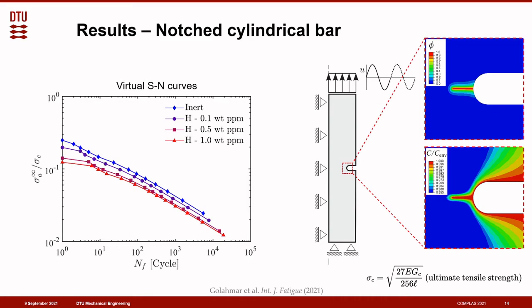And on the right side, I'm showing two contour plots. The one at the top is the evolution of the phase field parameter. The blue color corresponds to undamaged material points, while the red color corresponds to a crack. So basically, you can see how the model captures fatigue crack nucleation and propagation from a notch and in the absence of a stress singularity. And the other contour plot at the bottom is the hydrogen distribution, which is normalized by the hydrogen concentration of the environment. For example, this could be a part of an offshore monopile for a wind turbine, which is exposed to seawater. And you can see how the environment immediately occupies the space created with crack advance.